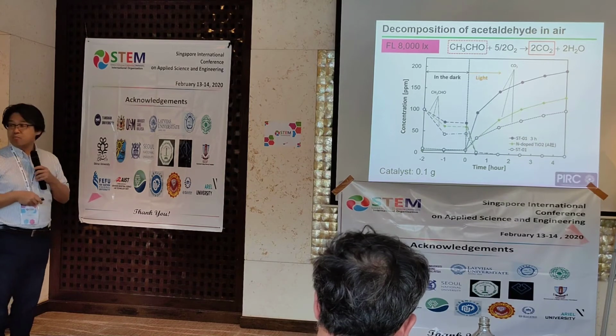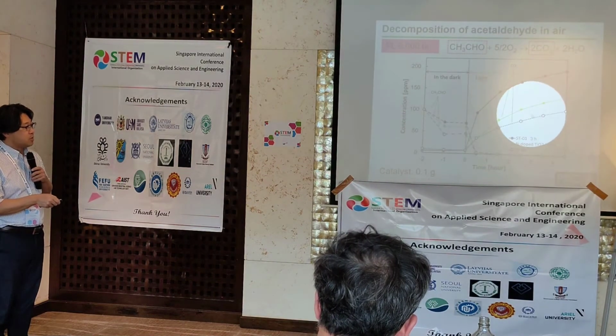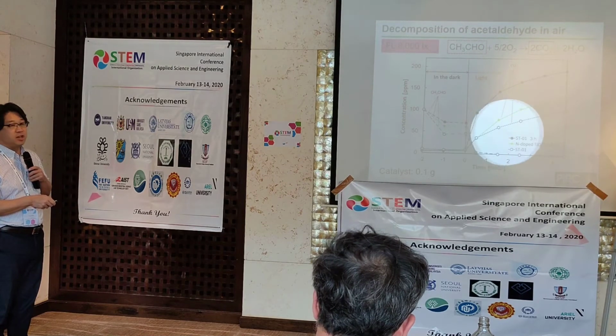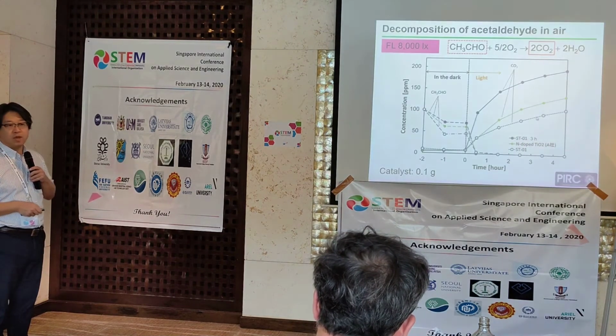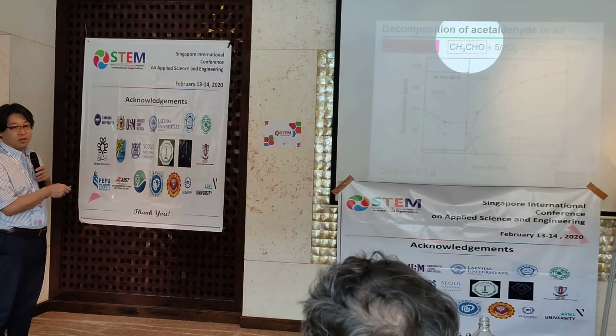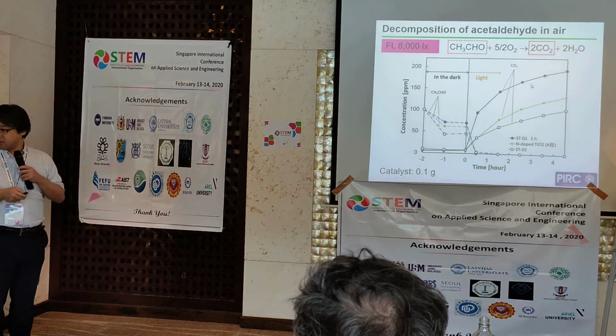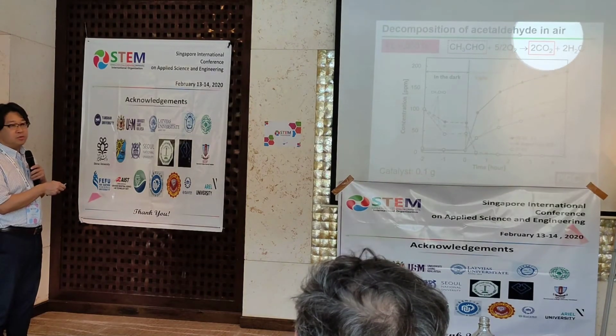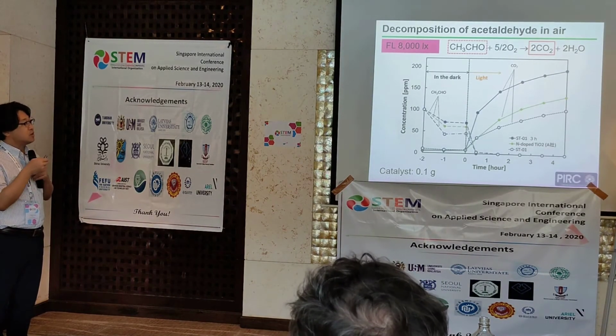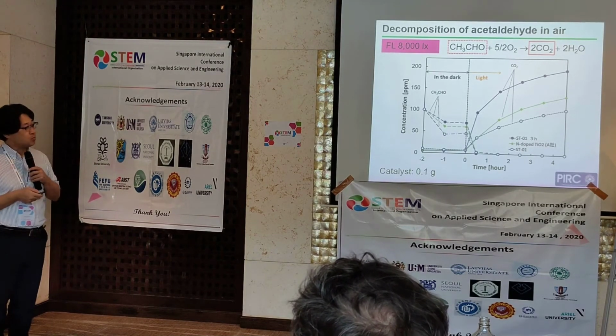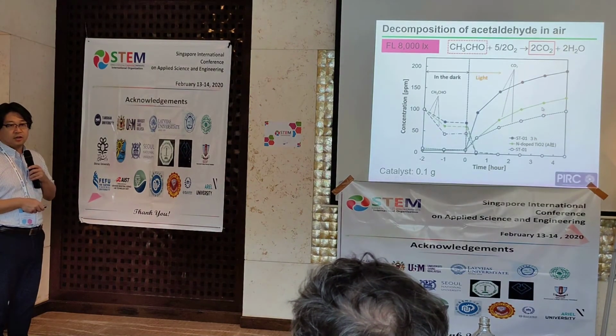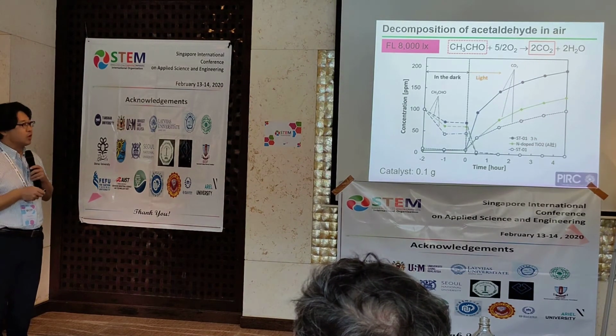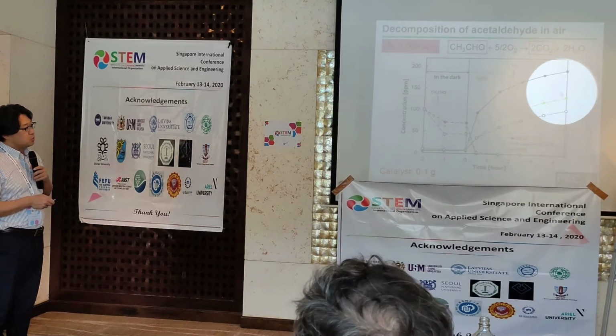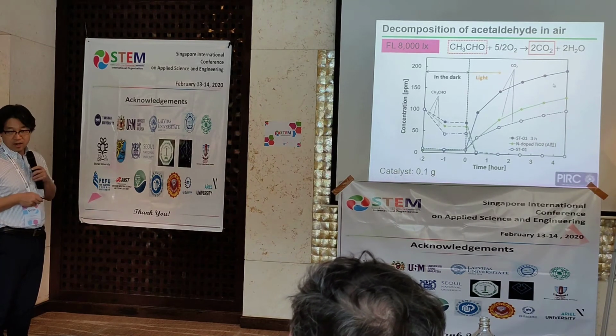Then, the important thing is this carbon dioxide. This white line is pristine TiO2. Carbon dioxide is around 100 ppm, almost the same as the acetaldehyde. But after plasma treatment, this material shows twice the carbon dioxide. That means the acetaldehyde is completely decomposed using this plasma-treated sample. This green line is a nitrogen-doped visible-light-active photocatalyst. So our material shows a highly active photocatalyst under a fluorescent lamp.